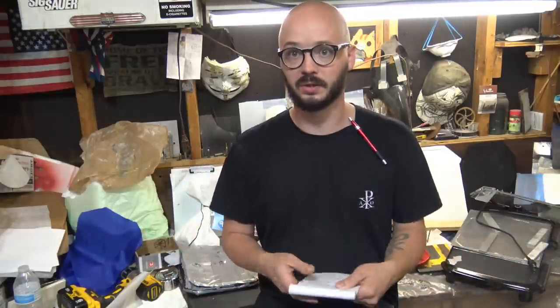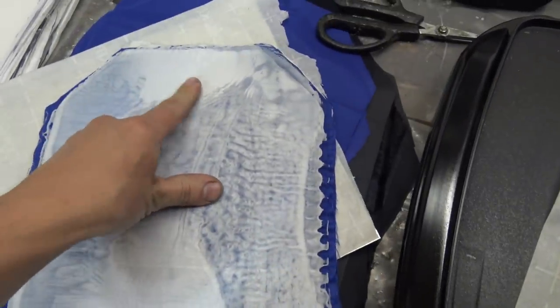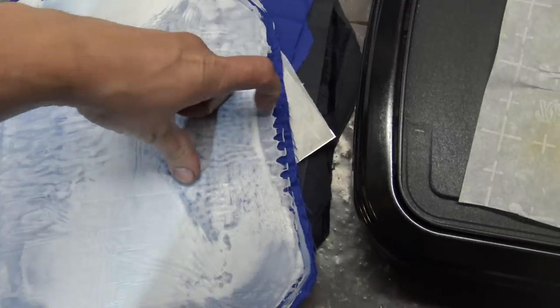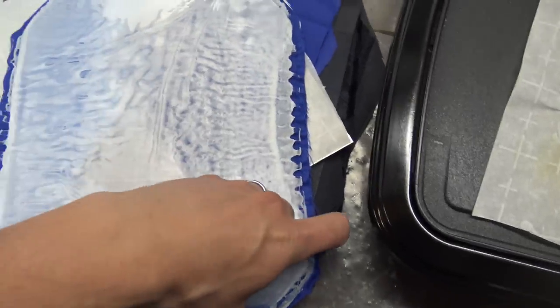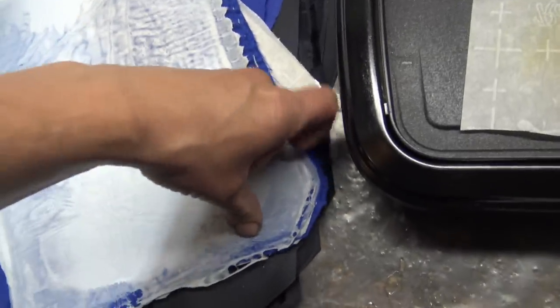All right, so let's go ahead and discuss how I made these with laminating. So I first started by trying my original method of laminating HDPE into fibers by placing high-density polyethylene film in between like 5 to 6 layers of nylon, clamping it in between 2 metal sheets, and placing it into an oven set at 350 degrees Fahrenheit for about 30 minutes.